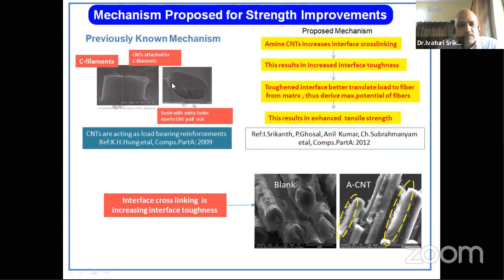So what people were proposing is, if you add nanotubes into the conventional carbon fiber, during the failure, this carbon fiber should get pulled out of the matrix, because nanotubes act as anchoring sites between the matrix and the fiber. To break these carbon nanotubes, you have to consume energy, because carbon nanotubes have high strength. Breaking them will consume a significant amount of energy, and that results in huge improvement in mechanical properties. People were thinking only dispersion is an issue. If you could disperse them well, you will get very good improvement in mechanical properties.